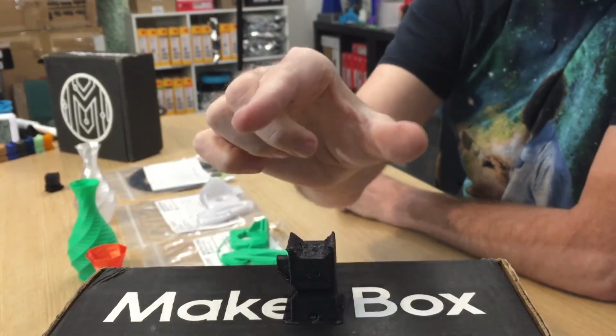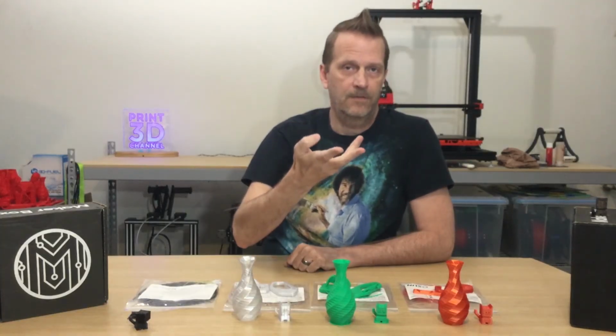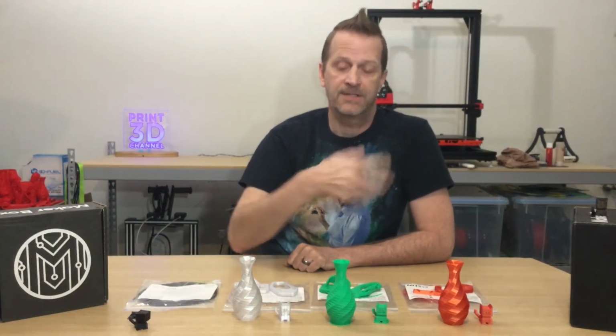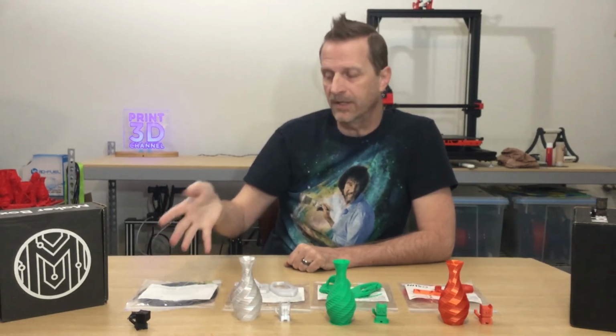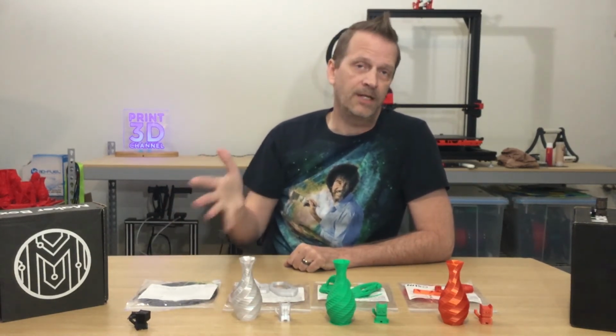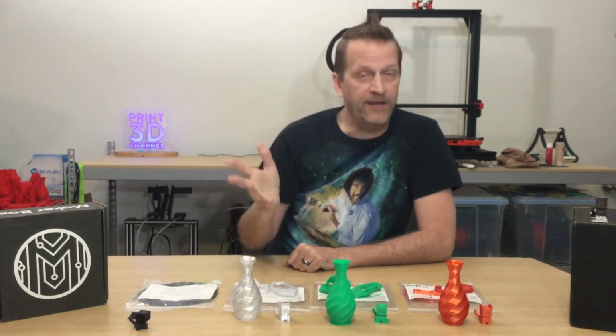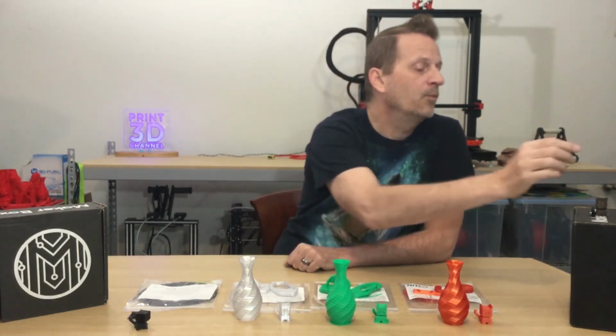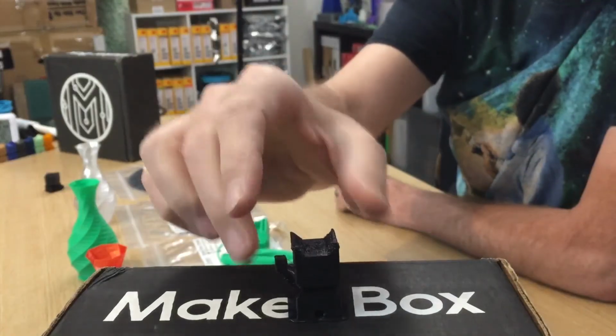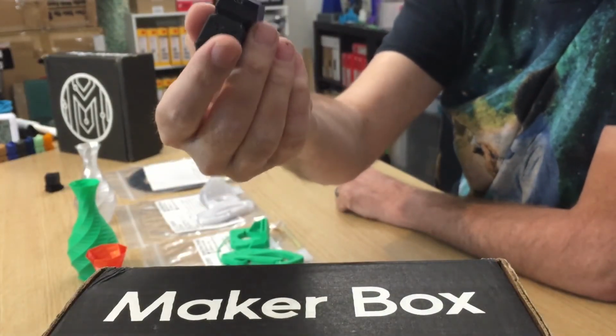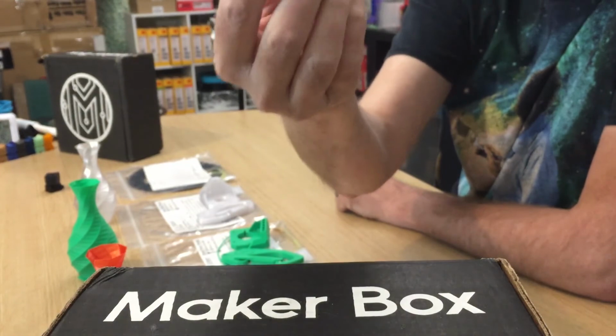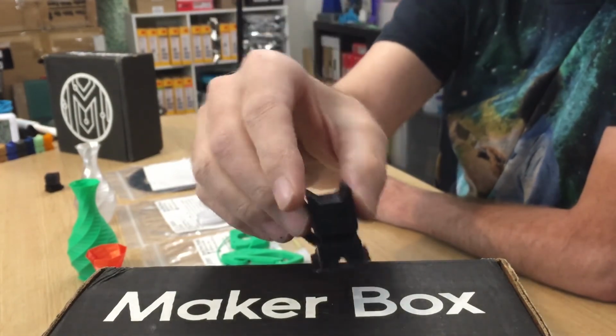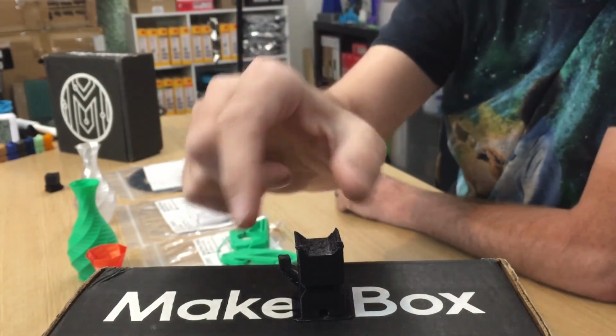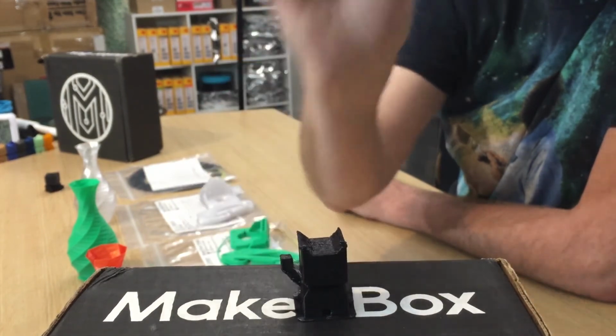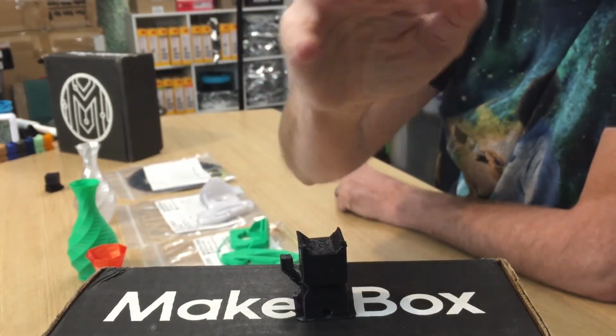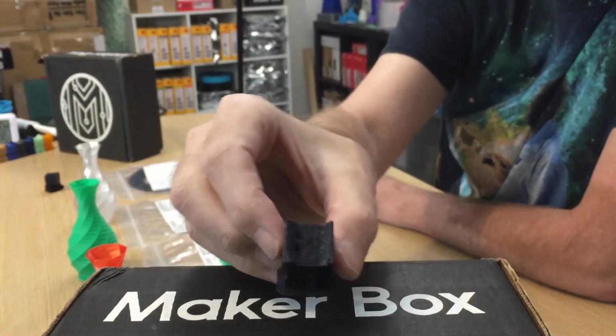So I let it go because I knew that the Magic Goo that I was also using as an assist for this, I should have added that in the beginning. I did use some Magic Goo for an assist on the bed adhesion just to make sure, hopefully it would stick down. And I have Build-Tack, and we're using heat. But the Magic Goo held it in place. It wasn't the surface of the plastic or the nylon that was holding it any longer. So up at the top, I felt like it was kind of moving just a little bit, just a little shudder to it. And it was, because the bottom had warped. So the top layers look really bad.